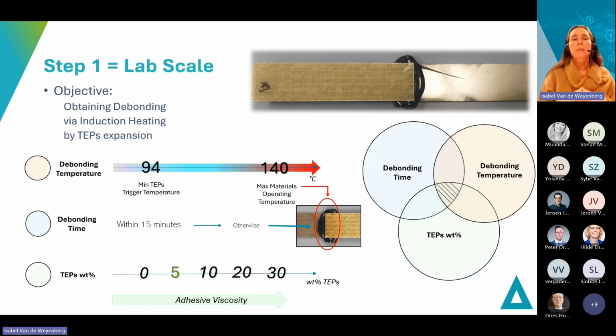And we use some thermal expandable particles in the adhesive layer to make the debonding much easier and more rapid. We have to make sure that the temperature of 140 degrees is not exceeded, because otherwise the composite panel will start to degrade. And also the debonding time should be limited to a maximum of 15 minutes to avoid degradation of the composite panel. And we've seen that only with 5% of TEPs mixed in adhesive, we could reach a really nice result, which I will show you in the next video. And this 5% will also allow us to work with adhesive viscosity, which is almost normal compared to the normal recipe.